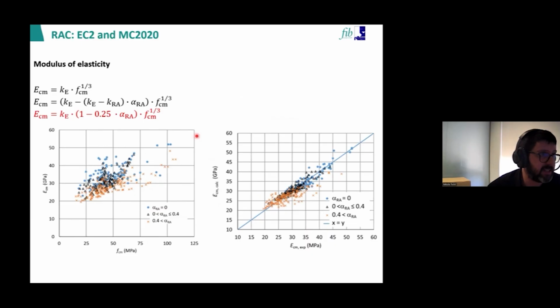For modulus of elasticity, as we said, the effects are significant. There are reductions in the modulus of elasticity because of the aggregates. And here we carried out a meta-analysis of collecting results from literature, splitting them into groups of percentage ratios, and calibrating simply empirically a reduction coefficient. So Ke times fcm to the power of 1/3 is the typical expression, where Ke depends on the natural aggregates, but you have a reduction of 1 minus 0.25 alpha.